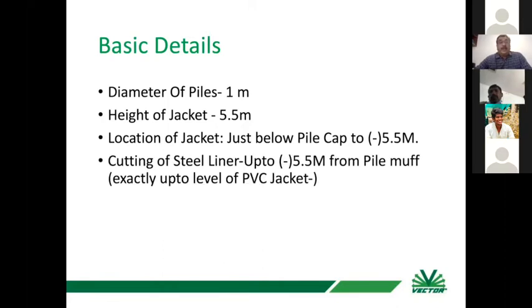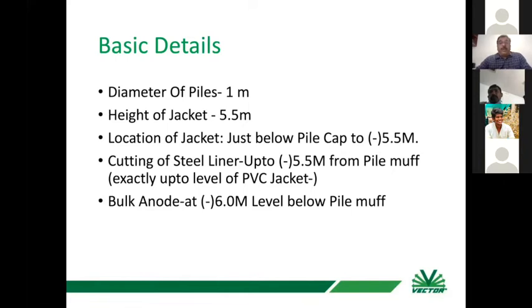And we installed the jacket from the bottom of the pile muff up to minus 5.5 meters, and a bulk anode was also installed at minus 6 meters to take care of the very high current demand over a period of time. The system was designed for 25 years, and the steel surface area was calculated.